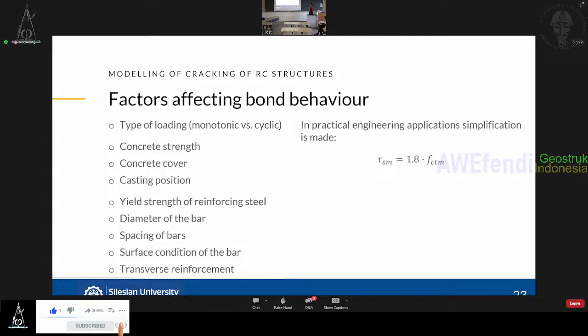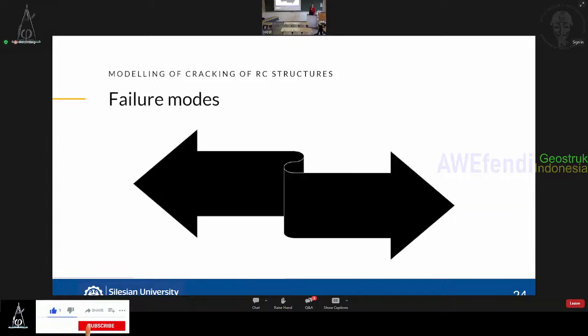And also something that has been widely discussed by Professor Schlicke is that usually in simplified calculations, we use the mean value of bond stresses. The most common value is 1.8 times the tensile strength of concrete. However, as has already been demonstrated to you very well, the bond stresses are dependent on the value of slip, and only if we include this in calculations can we really predict the cracks, so the number of cracks, whether one or more cracks would form, and what would be their final width. To do so, we need to introduce the bond law, and